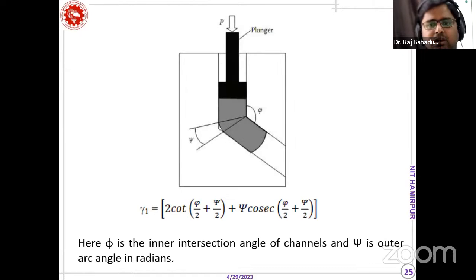Coming to equal channel angular pressing, this is a simple process compared to the other techniques, and relatively larger dimensional samples we can deform. So this is the channel. We basically have two angles, the outer arc angle and the inner intersection angle. The strain imposed depends on these angles. This angle is sometimes 90 degrees, sometimes 120 degrees, depending on the material. If the material is more ductile, we can deform the material by a 90-degree die. If the material, like steels, is not that ductile, then we can deform it by increasing the angle so that it can easily be deformed. So the strain imposed depends only on these angles, phi and psi.